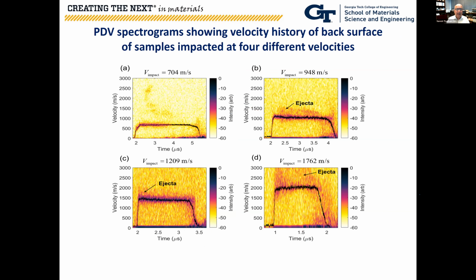Let me show you. These are examples of the profiles captured at different impact velocities, and there's a lot of information captured here. One thing you see at this low velocity, 704 meters per second impact experiment, is a hump, a knee, before reaching peak velocity. That knee is indicative of some type of mechanical rubberization, meaning the composite material is becoming rubberized.